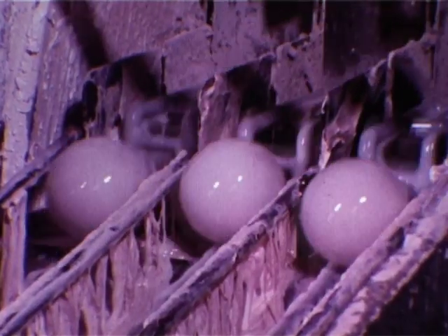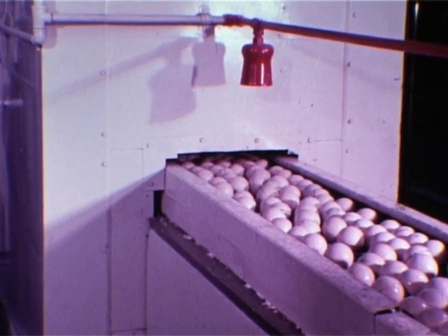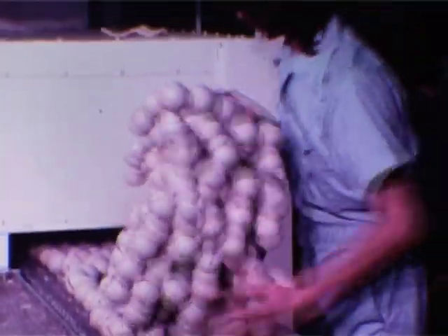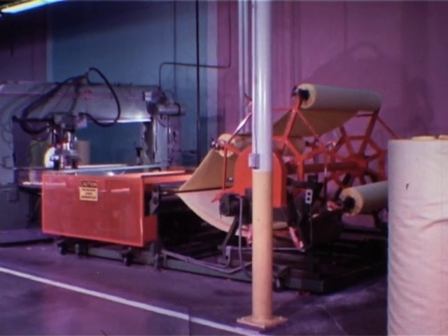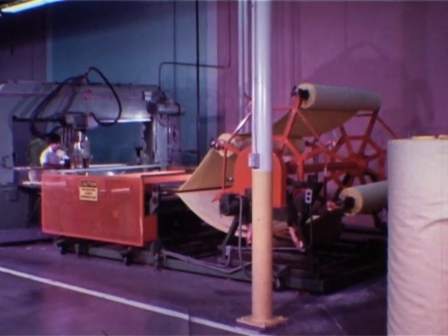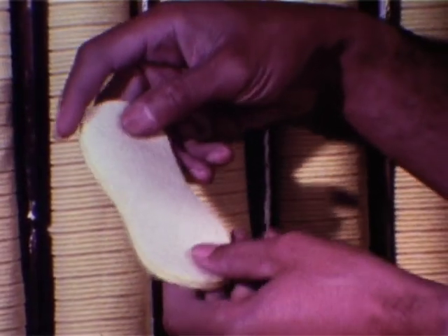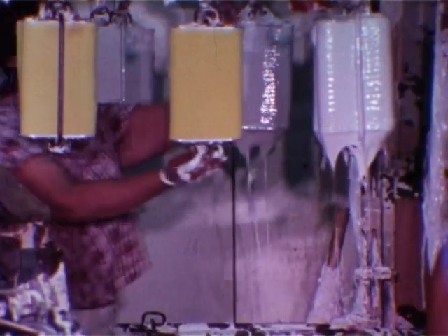From another bin, the freshly buffed centers drop into a trough-like conveyor for coating with an adhesive made from natural rubber. Drying in an oven is continuous. Pre-cemented, the balls are ready to have the covers put on. The cover material is a felt made of just the right, longest-wearing mixture of natural and synthetic fibers, pre-coated on one side with cement. Cutting is automatic, with each cover emerging in a modified dog bone shape. Stacks of covers are dipped in adhesive to make the edges tacky — these edges become the tennis ball seams.